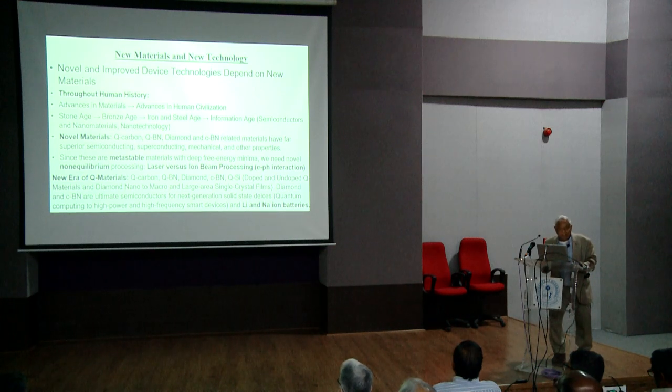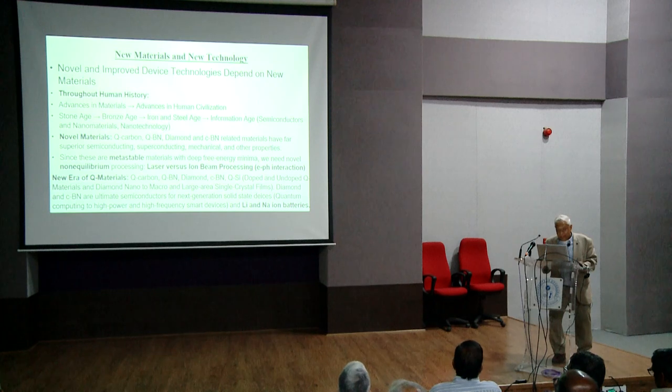However, there is a big challenge. These materials are metastable materials, but they have a deep free energy minimum. Diamond is the same way. It's a metastable material with a deep free energy minimum, and we can do whatever we want because it is stable. So, since they are metastable materials, we need non-equilibrium processing.